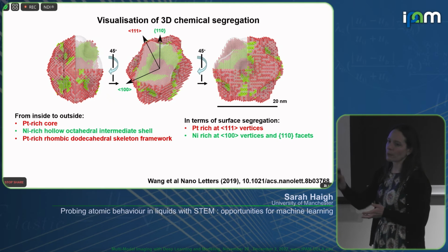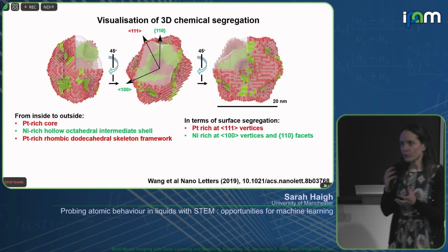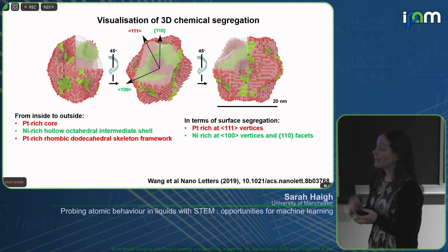And then we filled that with platinum and nickel based on the voxel concentration that we know for that nanometer by nanometer square region. In theory, you'd be able to do this type of analysis at higher spatial resolution, but you'd need more electron dose, so you need more stable particles, or indeed you just need to measure more particles. Okay,